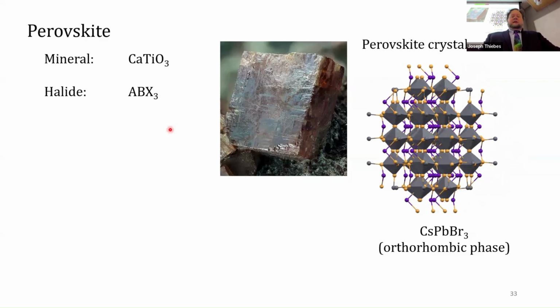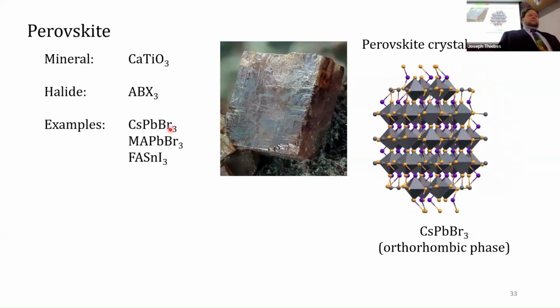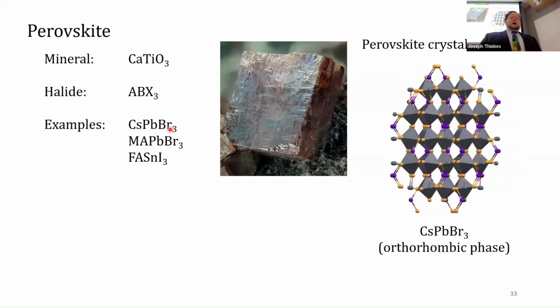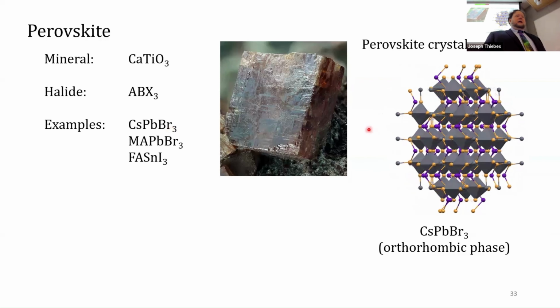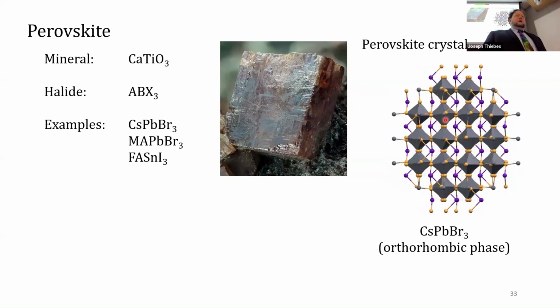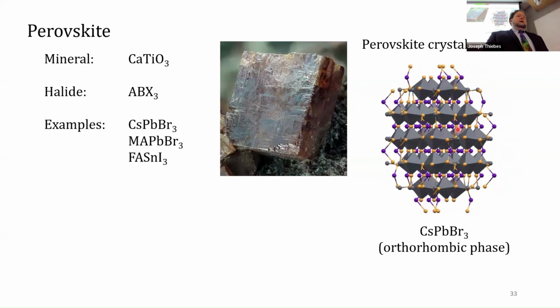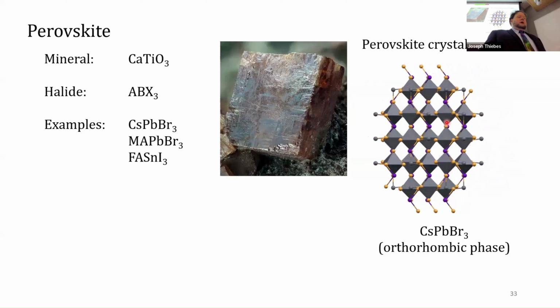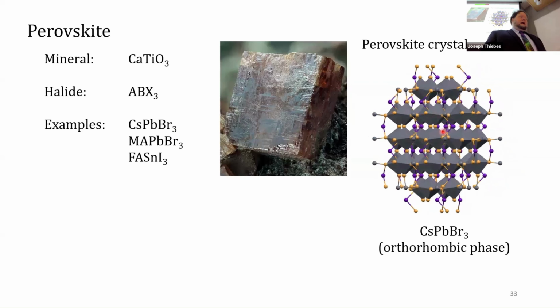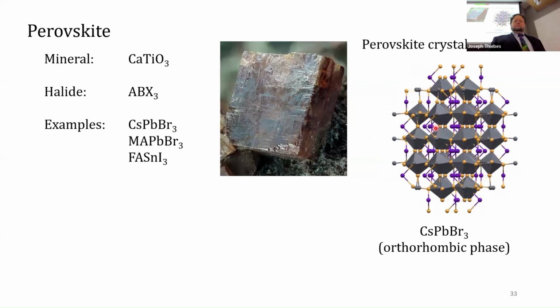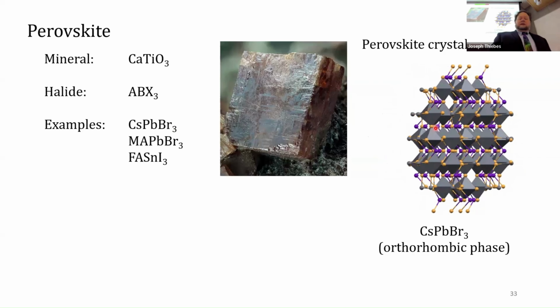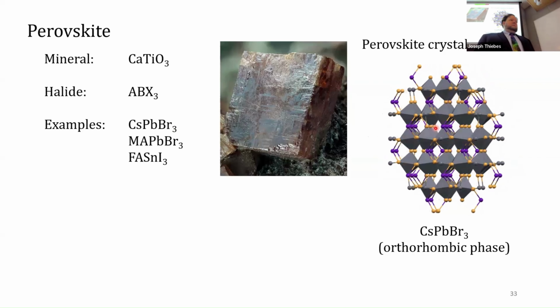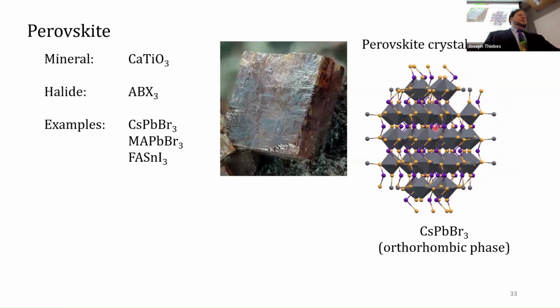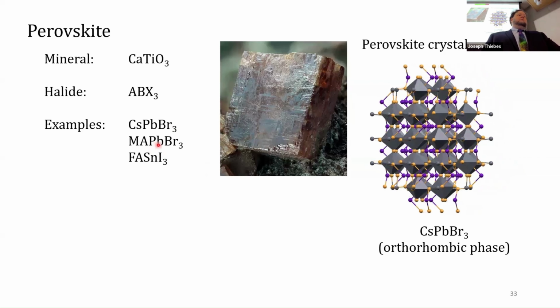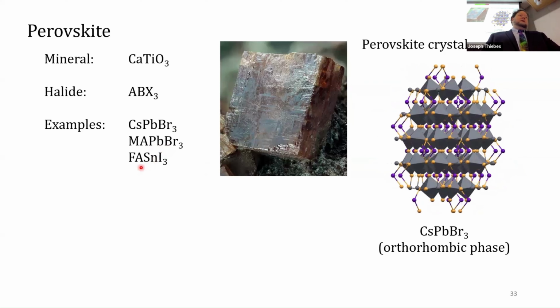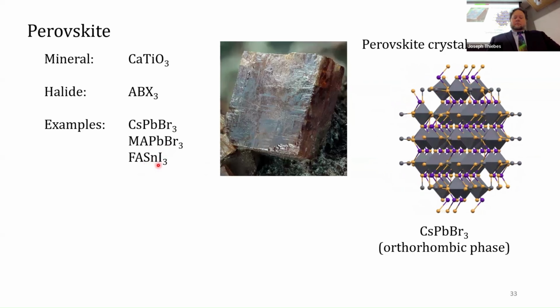And then the B is a divalent metal like lead or tin, and it's octahedrally coordinated to the halide anion. You can see those octahedra here. That's the lead, and then the gold spheres are the halide, in this case bromine. And they share the octahedral corners. These are some examples of halide perovskite: cesium lead tribromide, methylammonium lead tribromide, formamidinium tin iodide.